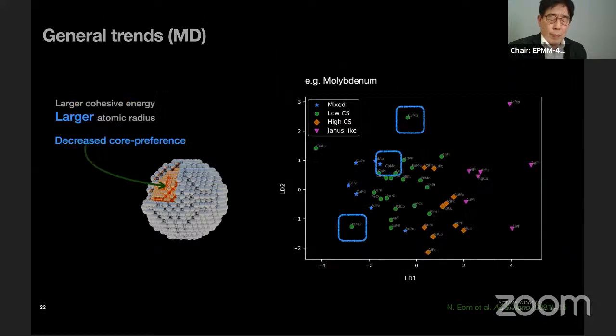But there were combinations that deviate from that majority. That is, in some combinations, the element with higher cohesive energy also has a large atomic radius. So in that case, the core preference of that metal decreases. This trend was seen, for example, in some of the combinations of molybdenum, because it has an unusually large atomic radius compared to its large cohesive energy.